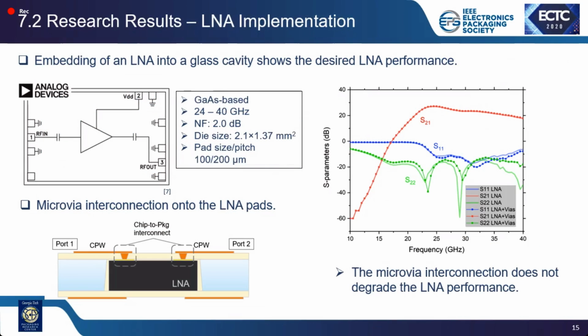So we try to embed an LNA from Analog Devices into the glass substrate that is shown over here. This LNA has a pad size and pitch of 100 and 200 microns, and the cross section is shown over here. And this LNA is connected to coplanar waveguides that are sitting on top, and that is connected through microvia interconnects.